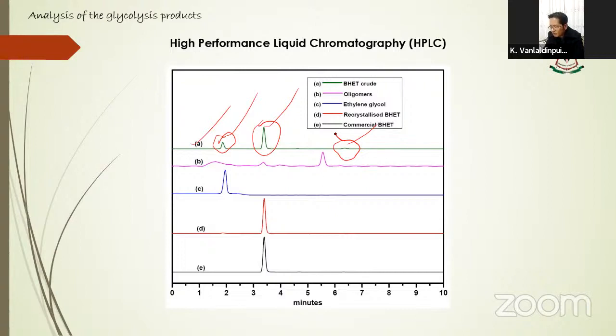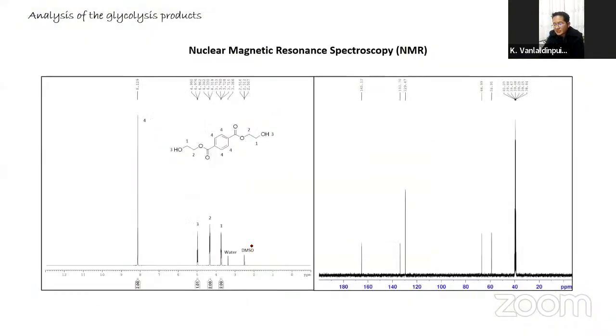We compared this result with commercially available products to confirm the formation of the desired product. C is ethylene glycol, and D is the recrystallized product. We recrystallized the crude BHET product, and we observed this peak in the HPLC data. Then this is the commercially available BHET. To confirm the formation of the desired product, all the results were compared with the commercially available products.